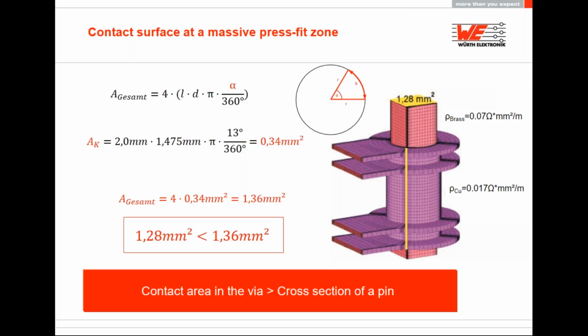And so the ratio will be better with a thicker PCB and lower with a thinner PCB, but it will still be perfectly okay. Additionally, the specific conductance of copper is 4 times better than for brass. So this means that an average angle of 13 degrees would be enough to ensure that the current can be carried by the pin and can also be carried by the contact area of the pin.